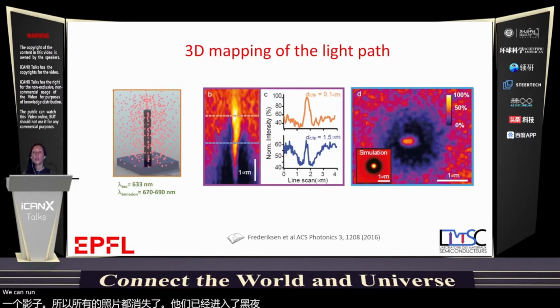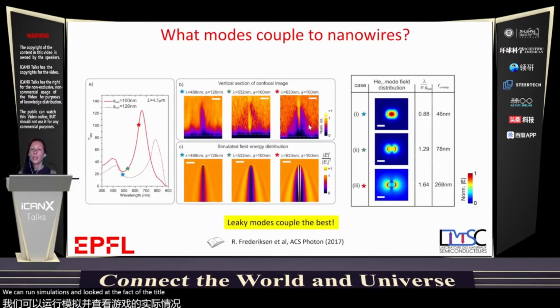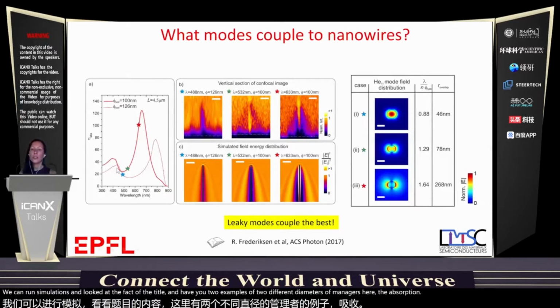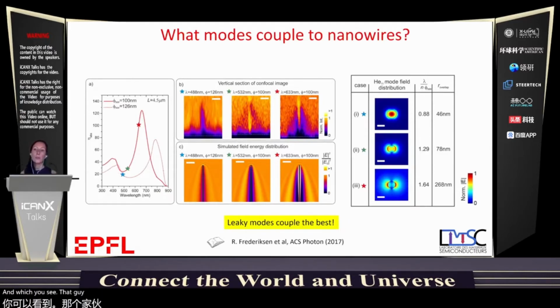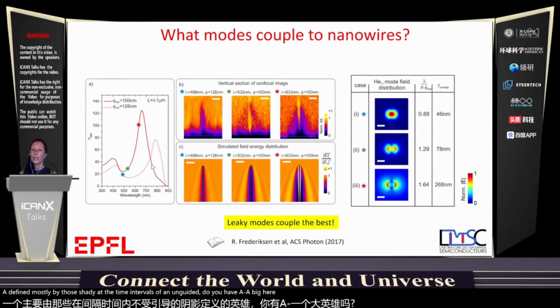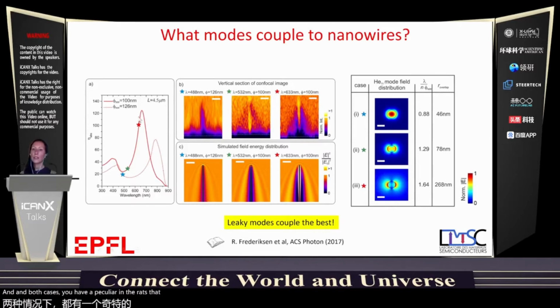We can run simulations and look at the effect of the diameter. And you have here 2 examples of 2 different diameters of nanowires. You see here the absorption cross-section, which is very different from what you would get on bulk gallium arsenide, and it's defined mostly by the shape and the diameter of the nanowire. So you have a peak here, and in both cases you have a peak in the red that depends on the diameter, and a second peak here. If we look now at these different points for the excitation wavelengths, we can see where the light is, and also the maps here for these different wavelengths.